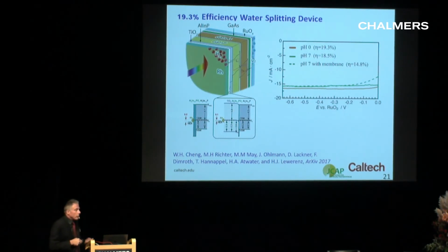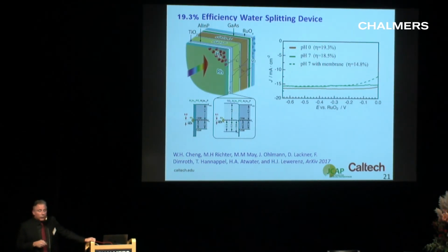So recently, we've been able to go beyond this. Nan was suggesting that maybe we could get to 20% as a community. Recently, we've gotten to an efficiency of 19.3% by carefully aligning the energy band positions in the semiconductors with the energy band positions in the catalyst, and reducing some of the overall reflection losses, some of the engineering things that he talked about. So this operates in acid conditions at 19.3%, but we can also operate very close to neutral pH, essentially pH similar to water, with a buffer, at 18.5%. So these are, by the way, also records as far as we know.